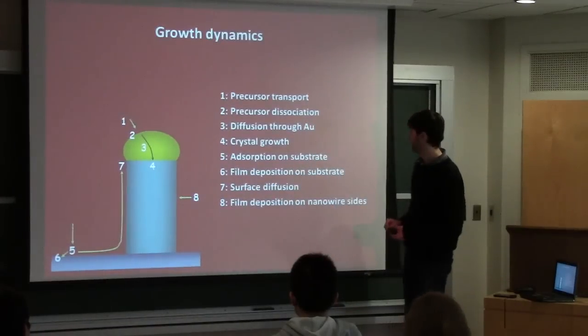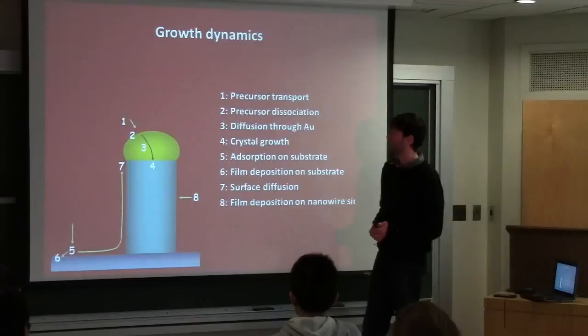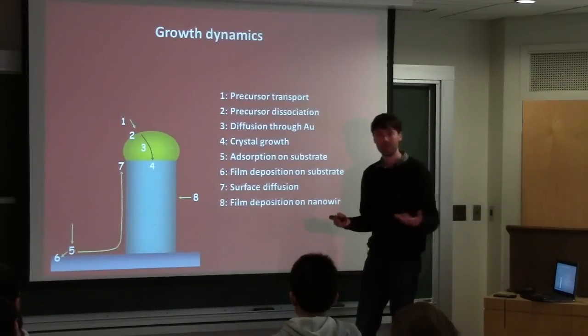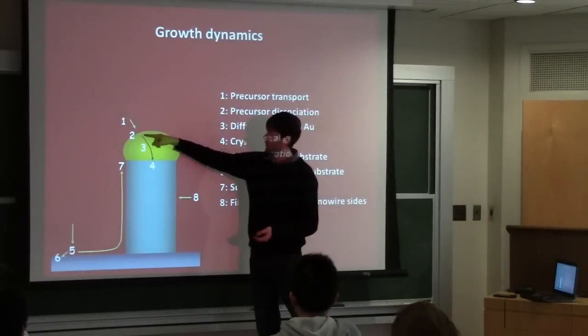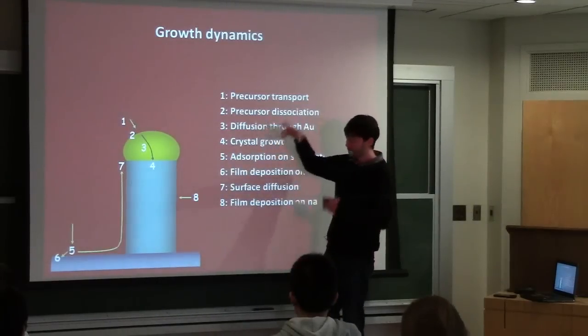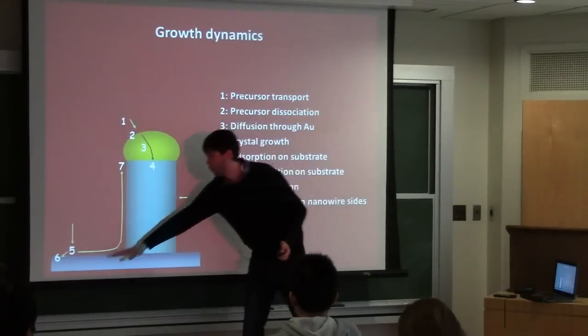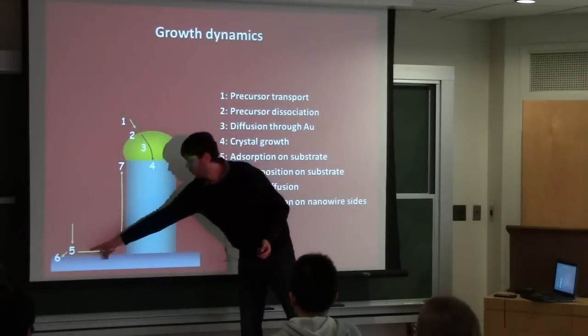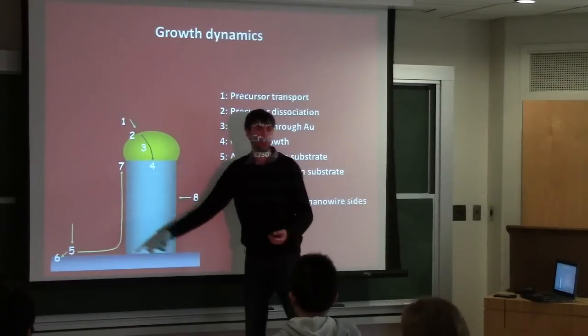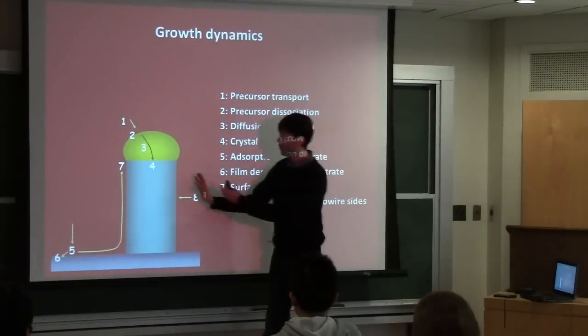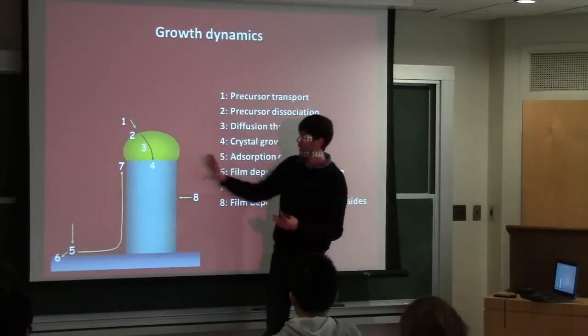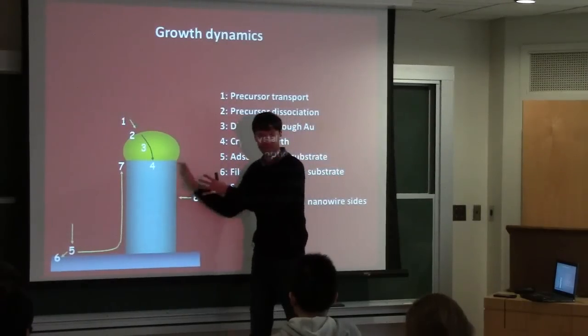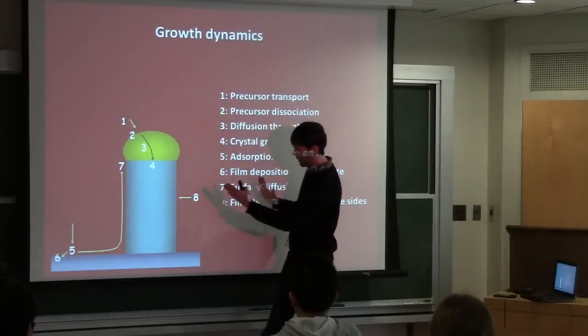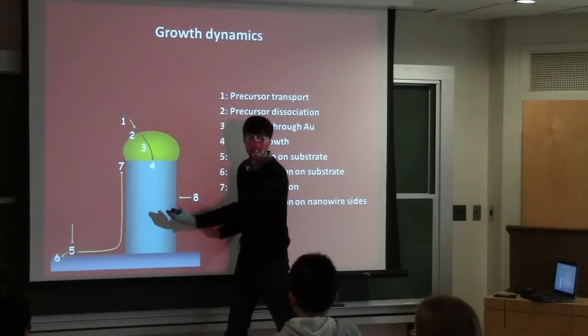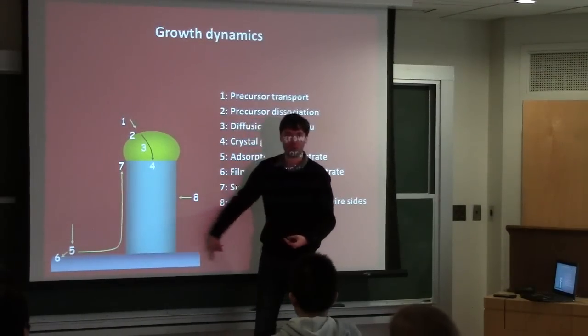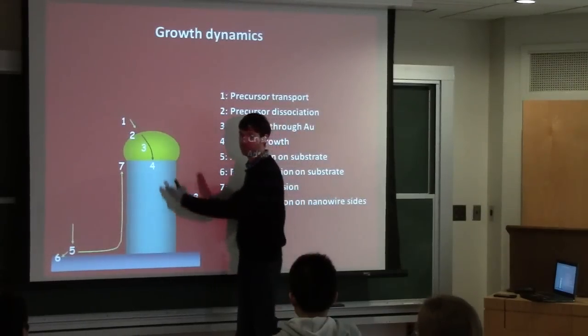And these can also be single crystalline. But that's not the only thing that's going on in the same reactor. You have other processes happening at the same time. Rather than going into gold and decomposing and precipitating, the same atoms can also hit the substrate and either grow a two-dimensional film, which is bad, or they can travel and diffuse up the surface. So there are different competing mechanisms. Another thing that can happen is radial growth. So you have this nanowire, and these atoms of indium and arsenic stick to it from the sides, making it fat. So sometimes the nanowire looks like a cone. That's because this part was around longer and it grows farther this way than the upper part. So there is some tapering to the nanowire.